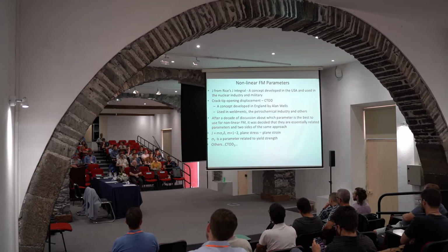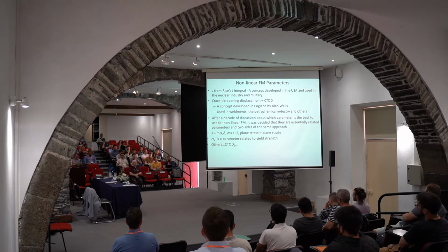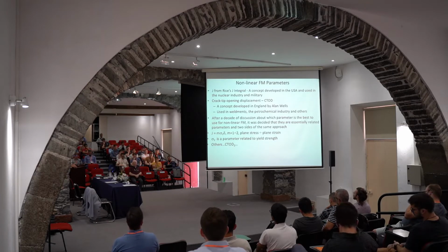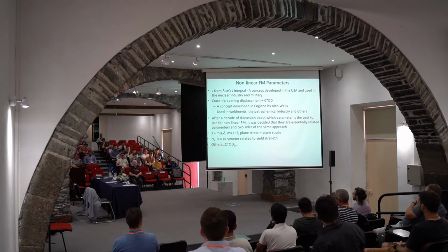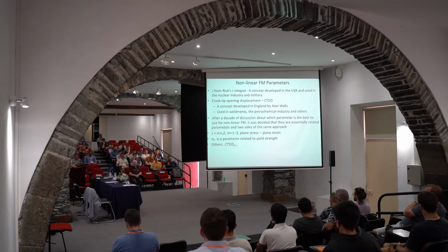Also, some other parameters like crack tip opening displacement 5, which means that it is measured 5 millimeters above or below the crack tip, as suggested by Dr. Schwalbe. They are quite useful, and they are maybe nowadays quite attractive because of new options for measurement like digital image correlation. It was quite difficult to measure such a parameter with clip gauges, but nowadays it is a relatively simple task.